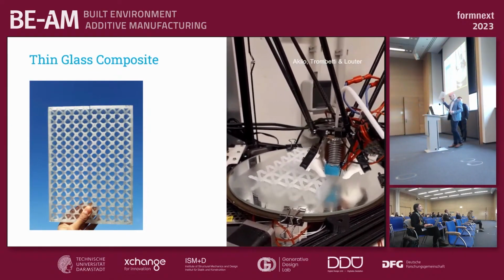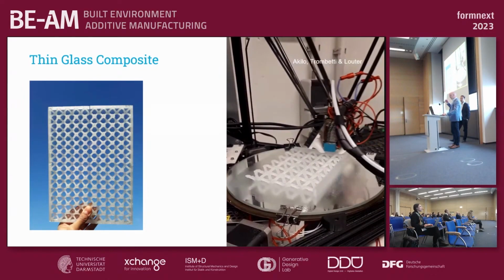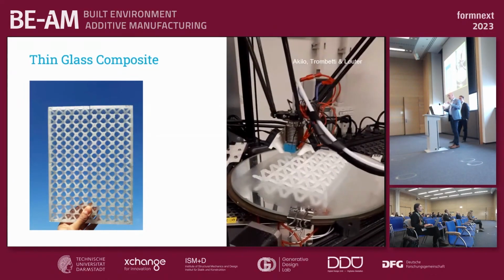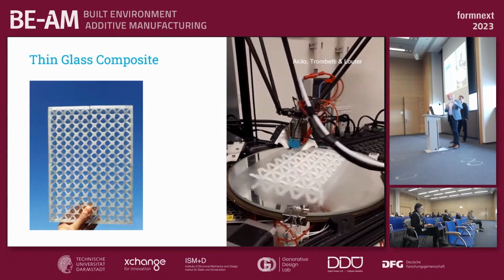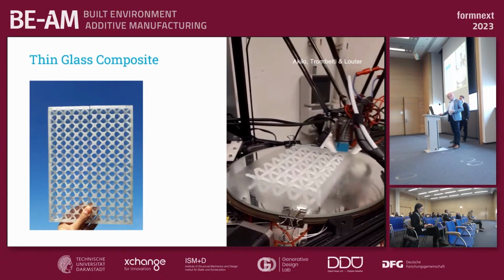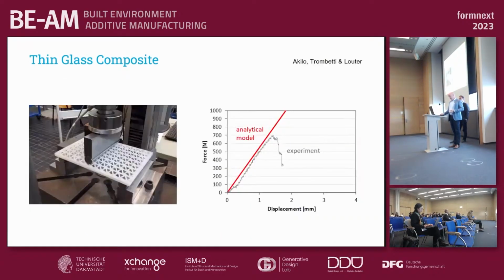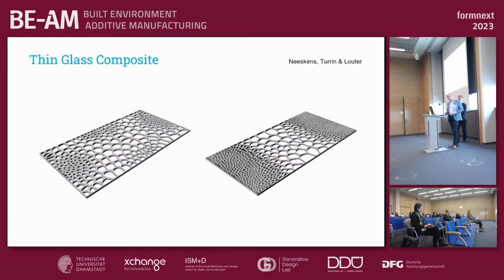That's what you see here, so that you have a pattern that is stiffening the thin glass, and that you create this very lightweight thin glass facade panel. Of course, we tested that at a very small scale, really A4 scale, and luckily it worked with our analytical model, so it combined very well.